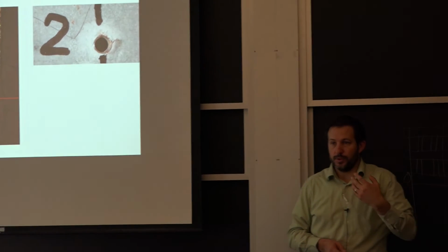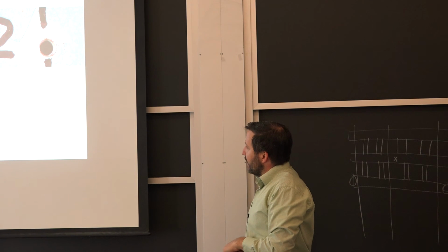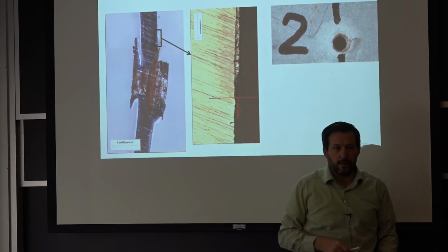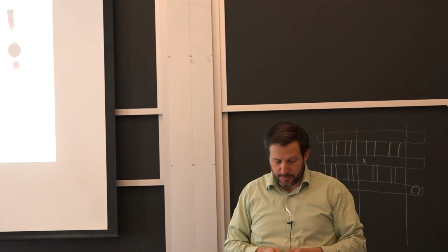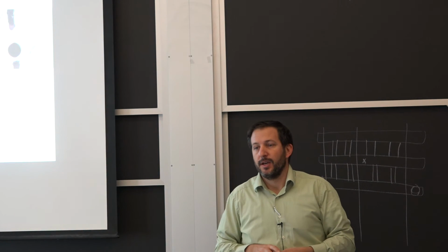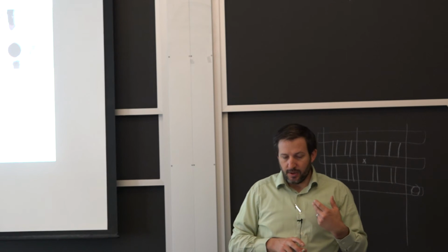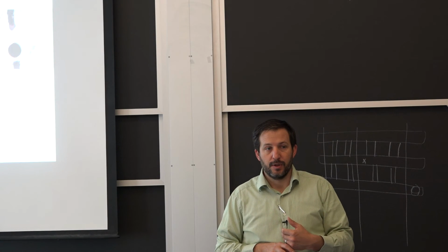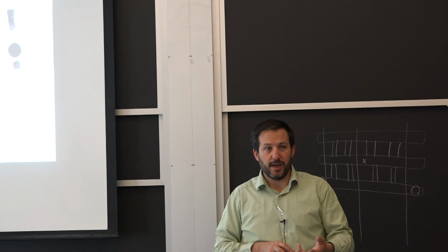And the next step was normal thickness loss. So if you want to estimate the life of the assembly that was put on just a couple of years ago, you have to think about the thickness of that sheet here where it's threaded and see how much time it's going to take to lose all of it. Is it a worst case scenario? Maybe sometimes, because it gets confined. Maybe it's actually going to be faster because you have a sacrificial process. But I think the main point is, instead of being a relatively dry environment like they have normally when they use these things, it was moist most of the year, and therefore something that would take, let's say, 25 years to start taking place, they had it going on just after 3 years.